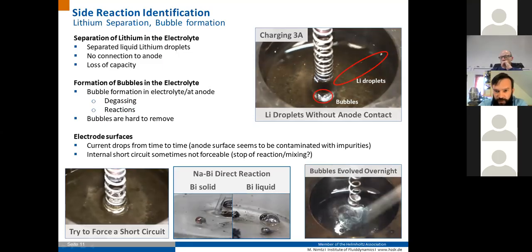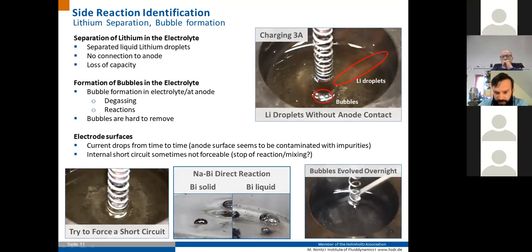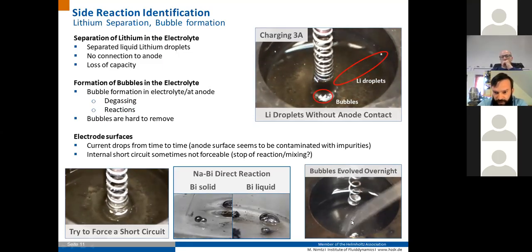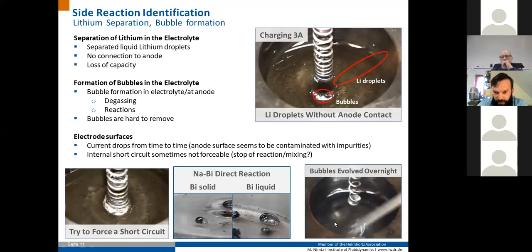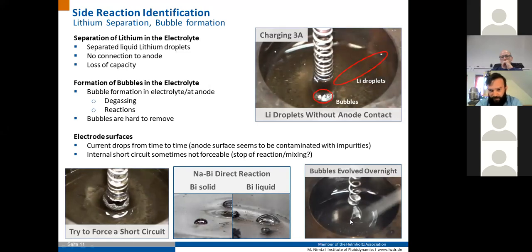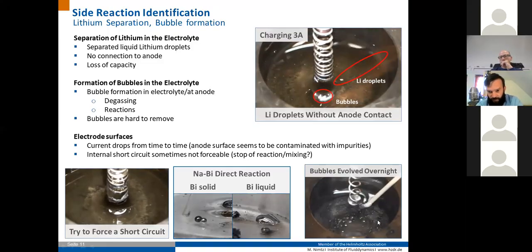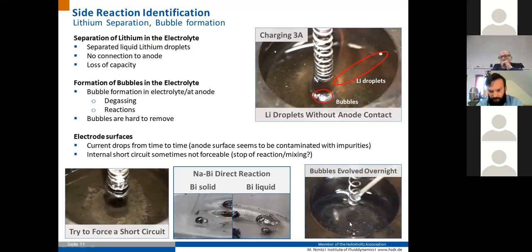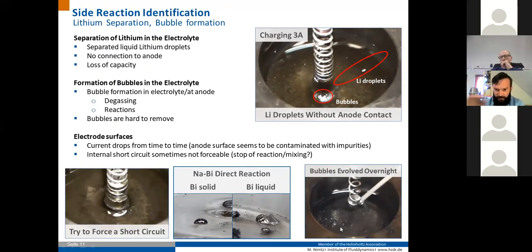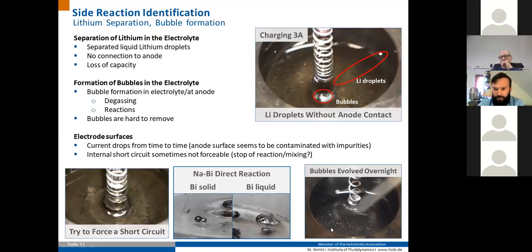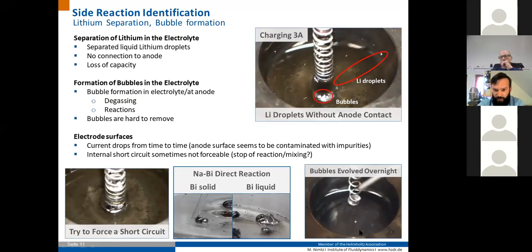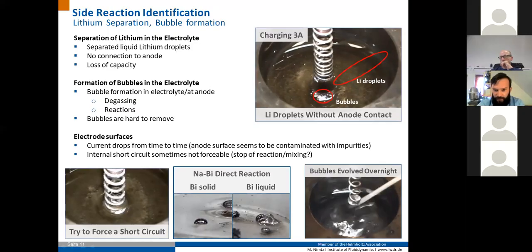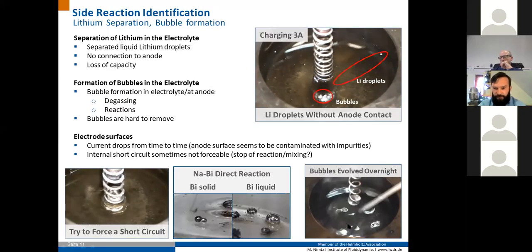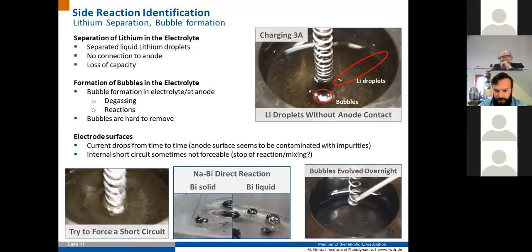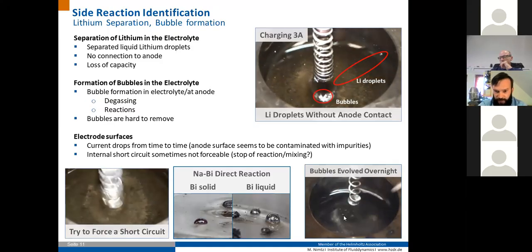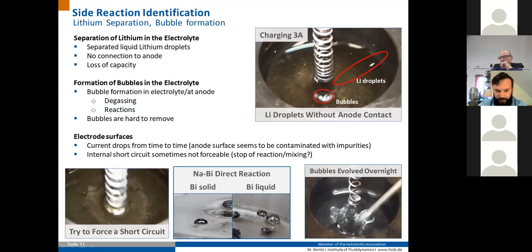Here the formation is at the lithium electrode, but as you can see in the lower part, overnight there was a formation of lots of gas bubbles at the bismuth electrode below the electrolyte, and these gas bubbles stuck in the interface layer between electrolyte and bismuth and were quite hard to remove, as you can see here, which is also something you would not expect due to the large density difference between the gas and the electrolyte mixture.